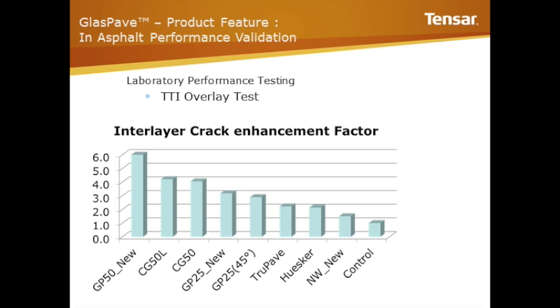What's interesting is next to the paving mat, we have 2 composite grids. That's a glass grid attached to a fabric. And remember I said that with the fabric, you lose efficiency. Well, look at that. You lose 1/3 of the performance of the product simply by including a fabric with the grid. So those 2 composite grid specimens next to the Glasspave on the left perform 1/3 less.